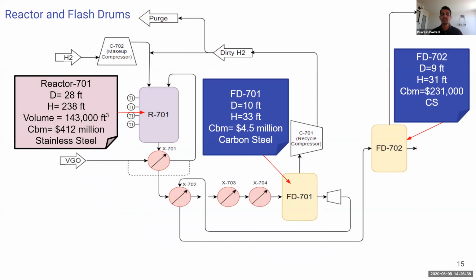Our reactor was quite huge with a diameter of 28 feet, height of 238 feet, with a volume of 143,000 cubic feet. The total CBM of our reactor was $412 million. The material of construction for the reactor was stainless steel to avoid hydrogen attack at higher temperature. Our first flash drum was quite expensive with a CBM of $4.5 million. And then the second flash drum was less expensive because of the lower flow rate going into it, with a CBM of $231,000. The material of construction for both flash drums was carbon steel.